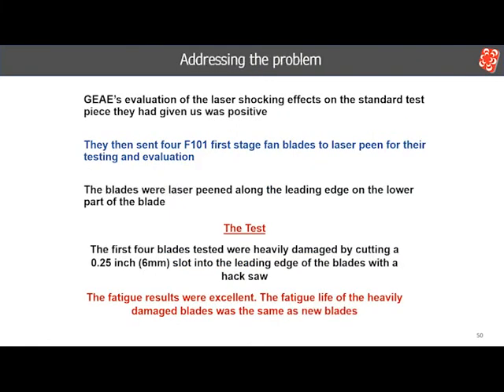After evaluating the laser peen test piece, GEAE sent 4 first-stage fan blades for laser peening. They were to be laser peened along the leading edge up from the platform. When the 4 laser peened blades were returned to GEAE for testing, they damaged them many times more severely than a nick. They used a hacksaw to make a 6 millimeter deep notch in the leading edge. After testing them, the results were almost unbelievable. They tested like new blades. There was no need to pursue optimization of the processing parameters. With this result, further testing and planning for implementing the process on the blades began.